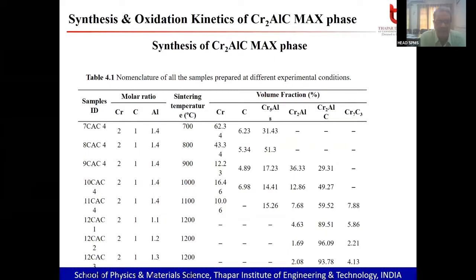Right now I will not be talking too much, okay, because I have become a little bit tired now. You can see these are the different class sample IDs, where we can see chromium, carbon, aluminum. We have synthesized Cr2AlC. This is one category of MAX phase. Cr2 is 2. So Cr2AlC MAX phase is what we have worked on. What I want to illustrate here is that under different experimental conditions, with the content of chromium, carbon, and aluminum we have taken, we are not able to get a MAX phase. Rather, we are able to get carbide, aluminum carbide. So this is a difficult task.